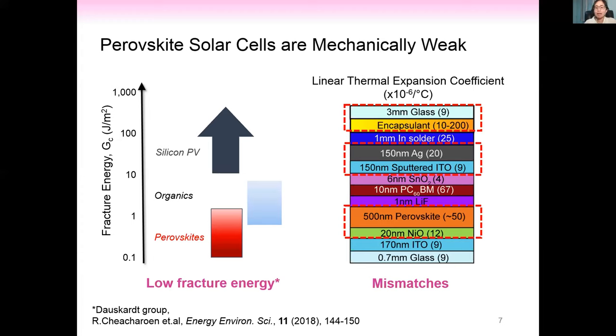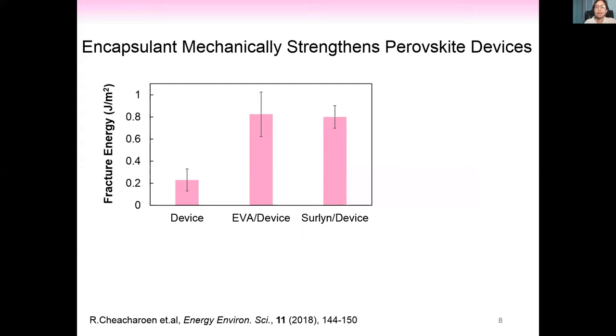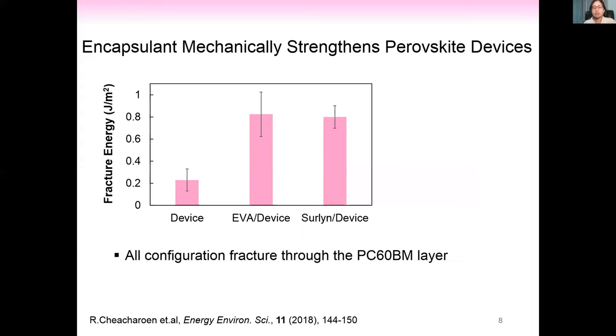Choosing a low elastic modulus is only one aspect for encapsulant selection. Chemical reactivity must also be considered — especially for the most aggressive damp heat test at 85°C and 85% humidity. Heat can cause metal species to migrate and degrade perovskite, and iodide leaving perovskite can react with metal. A pressure cooker test at 120°C and 100% relative humidity gives results within 20 hours, screening encapsulants far faster than the 1000-hour damp heat test.